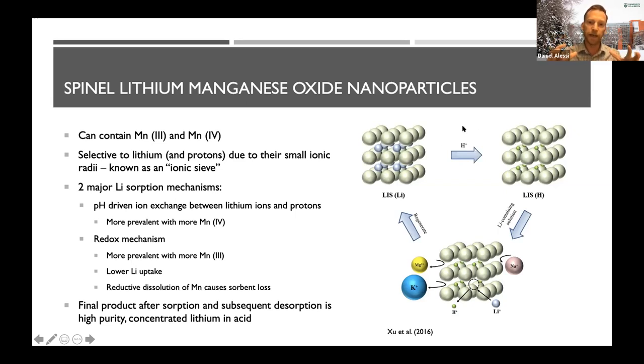And because the volume of the acid that I added is far less than the initial brine volume, the concentration of lithium in the resulting solution is way higher. So for example, you might go from what we see here, 40 parts per million lithium in the brine, to 1,500 parts per million in the concentrate. And the other great thing that I'll show you here in a bit is, of course, you've excluded the majority of these things you don't want from the brine: sodium, magnesium, potassium, all those other things. And that, in a nutshell, is what these DLE technologies, direct lithium extraction technologies, are about. This is just one example of a material. Good, I think that covers the slide, so we can move on.